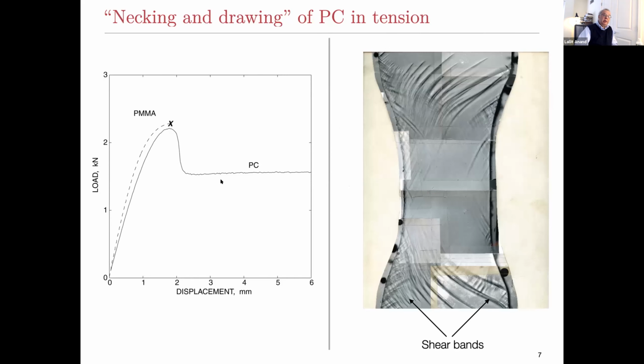The polycarbonate, on the other hand, because of that strain softening, will neck and draw out. Here's a specimen of polycarbonate. Originally this was straight, but now it's necked down, and the plasticity in this is due to the shooting out of the shear bands into the undeformed region. I'll show you a movie of this drawing out process a little later.